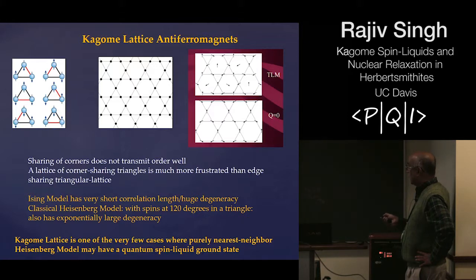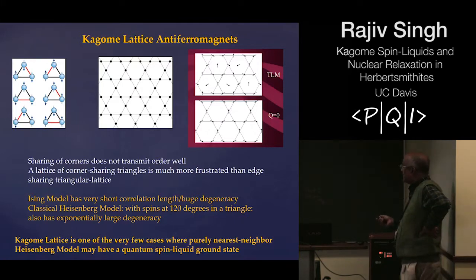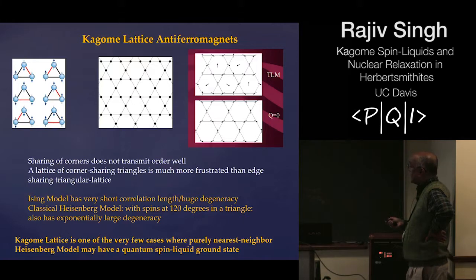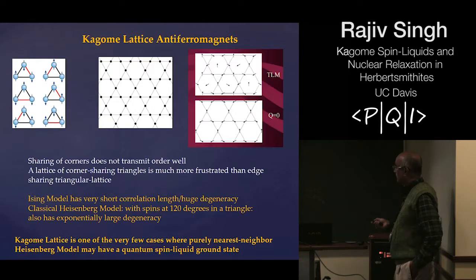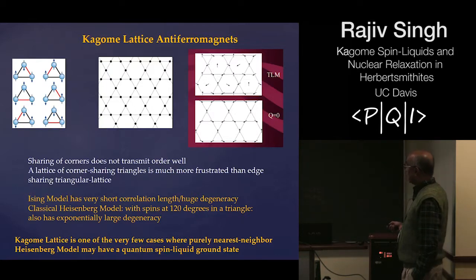The Ising models on the Kagome and triangular lattices are both exactly soluble. It's known that the triangular lattice model remains disordered down to 0 temperature, but the correlation length diverges. Essentially 0 temperature is like a critical point. But for the Ising model on the Kagome lattice, all the way down to 0 temperature the model stays disordered with a correlation length only of order the lattice constant. So really strongly disordered, and there's a huge ground state entropy in both cases, and on the Kagome lattice a very large fraction of the states remain accessible down to 0 temperature.